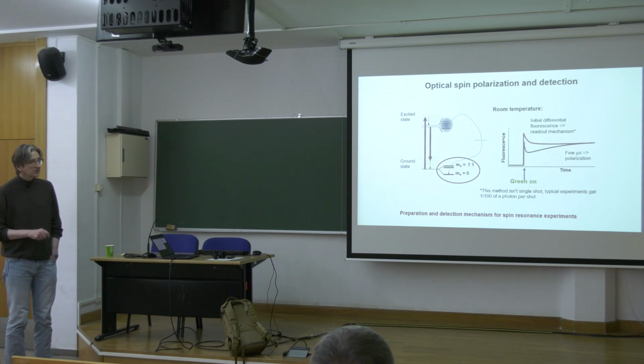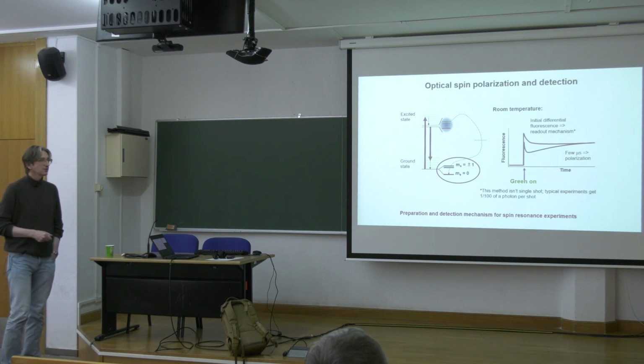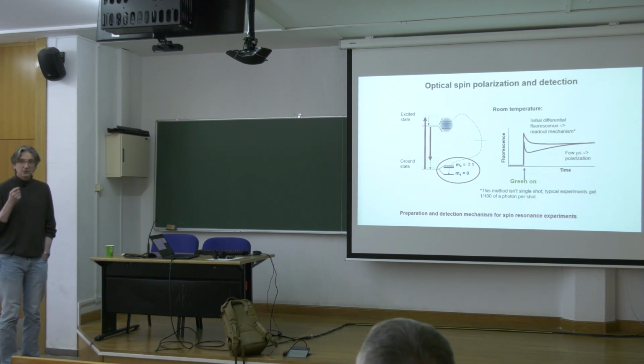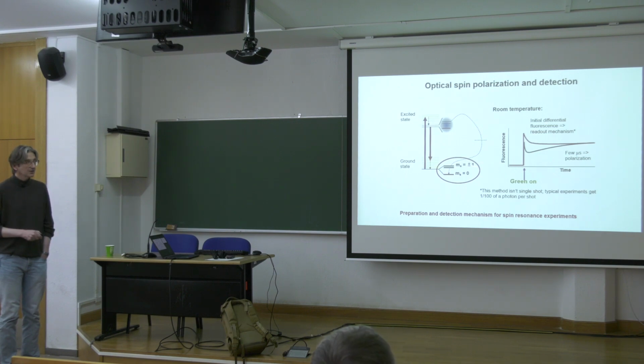So if you do experiments where you shine a laser on your system, switch the laser on, and measure fluorescence intensity, the response of the NV center in terms of the number of emitted photons will be different for ms equals 0, which is brighter, compared to ms equals plus minus 1, which are darker. So this provides you a way to measure the spin state with very, very high efficiency, because the optical technique of measurement can be very effective.